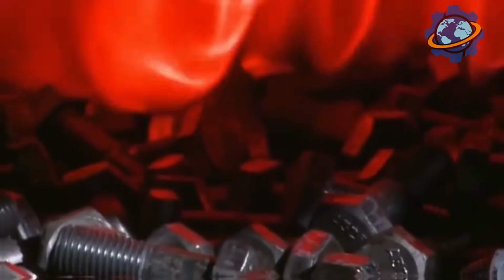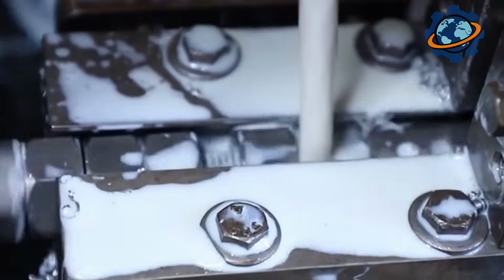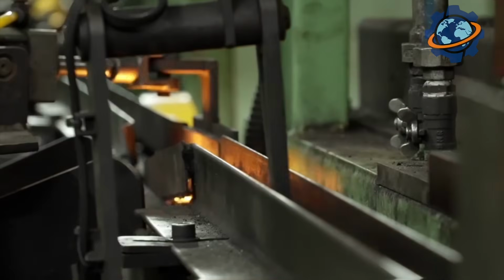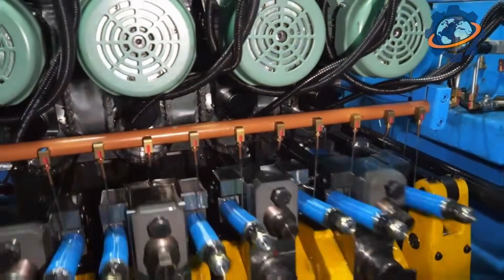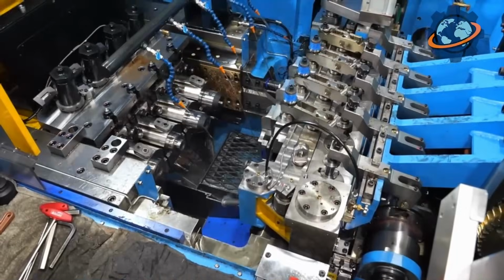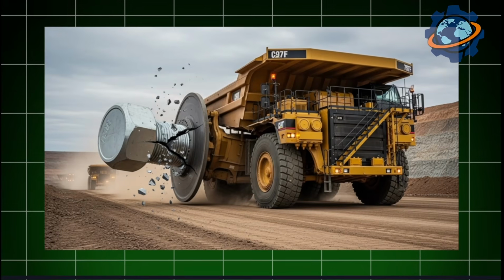This means the bolt only starts to deform when loaded to 162,000 pounds per square inch. For comparison, a regular bolt from a hardware store is marked 5 and 8, or 8 and 8 at most. Strength, just 50 or 80,000 pounds per square inch. Put a bolt like that on a Caterpillar 797F and it'll snap the first time you hit the brakes.